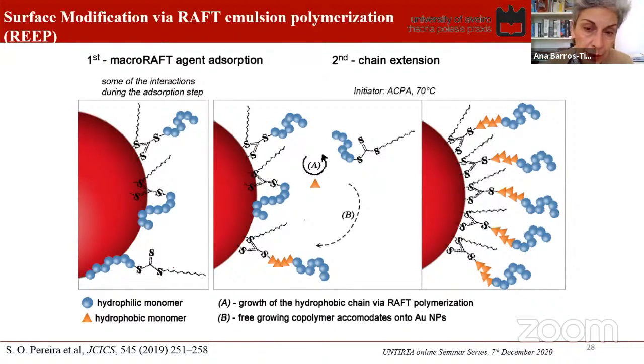what happens is the new chains that are formed in the medium will try to also adsorb at the surface of the gold nanoparticles. So this will force the chains to point outwards in order to accommodate as many chains as possible on the surface of the gold nanoparticle. So this may be improved further, but for the moment, the amount of polymer anchored on the surface of the nanoparticles proved to be sufficient to change the properties of the gold nanoparticles.